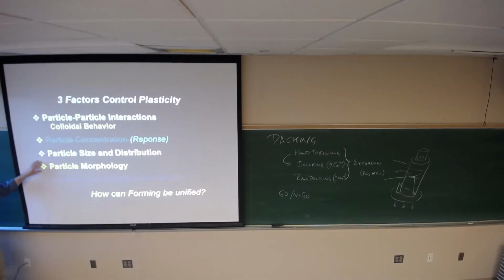My particle size, distribution, and morphology. These 2, interestingly enough, are typically fixed. I have a given body composition. I just fixed my particle size and distribution. Okay, I pick EPK and OM4. I just fixed or locked in my particle morphology. Now, if I take out EPK and I put in, say, Grolleg, now I just changed both the particle size distribution and the morphology of that particle. Grolleg is larger, plate-like particles. EPK is smaller, and then the aspect ratio is a little different. It changes a little bit. So you might see that a body created with Grolleg compared to a body created with EPK might feel different or have different plastic characteristics.